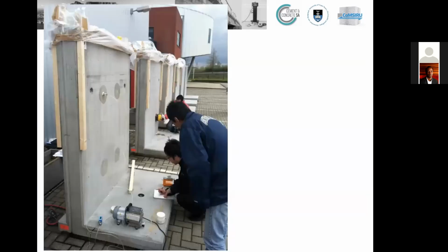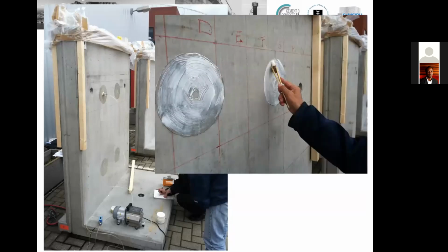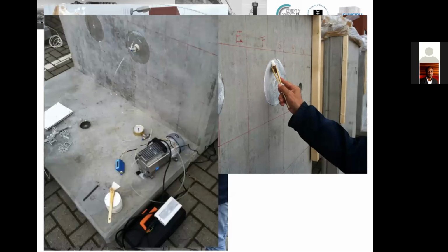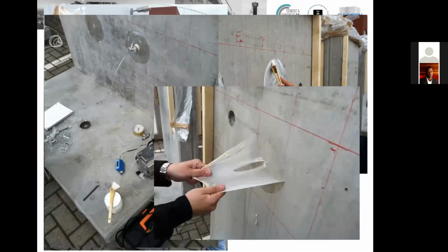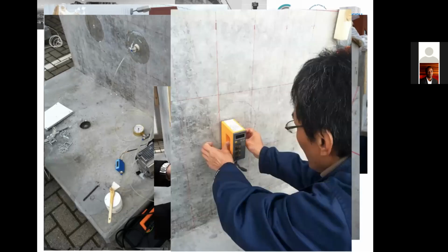So what you see in this picture, that is a Japanese method which measures oxygen or like air permeability on concrete, where a silicone is applied to the surface with the center remaining without silicone. And on the little center portion, as you can see on the left, the oxygen permeability is measured, whereas the neighboring concrete surfaces are sealed off. And then you can just remove the silicone after measurement.